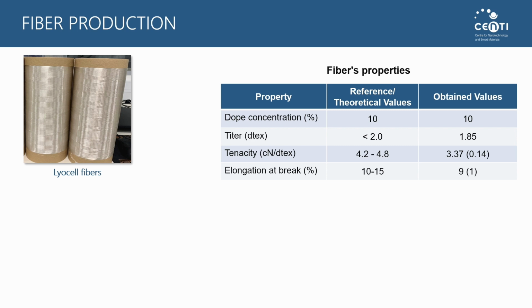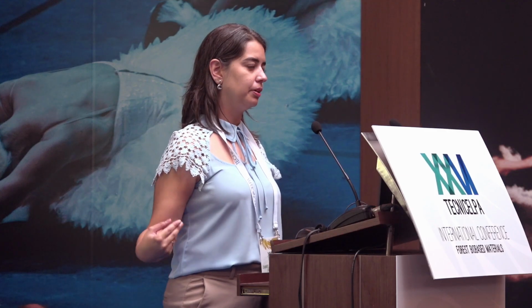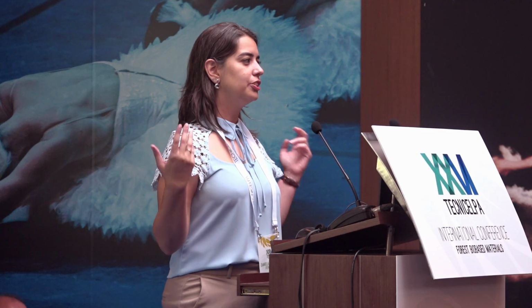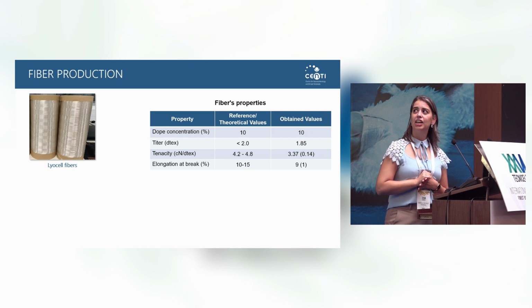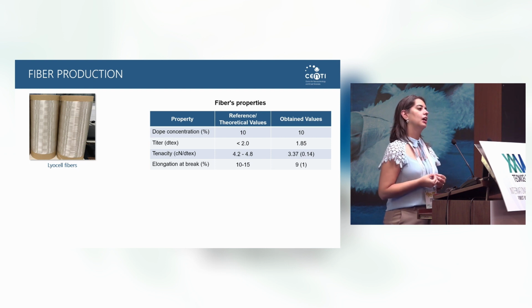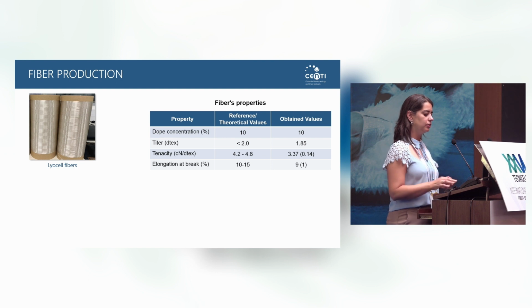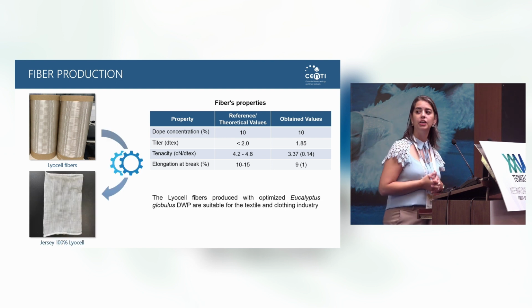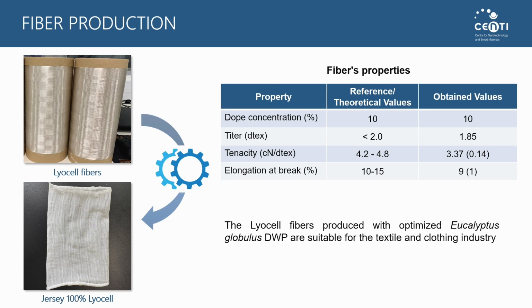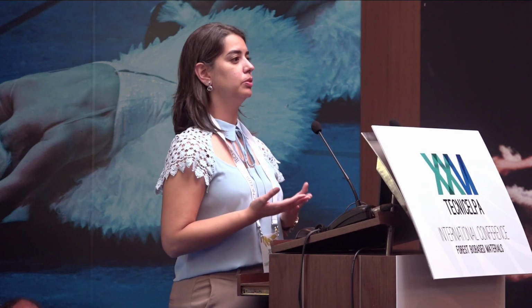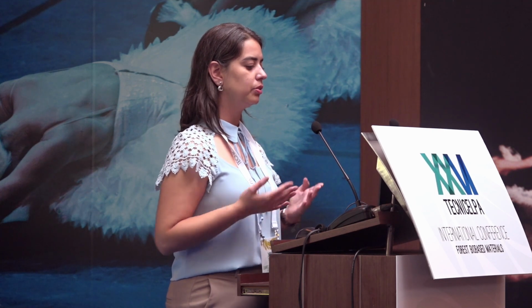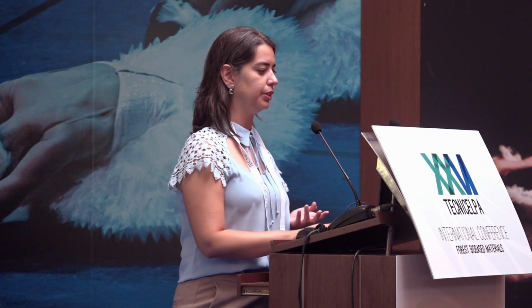So we got our fibers, our first 100% Portuguese fibers made with pulp produced here in Portugal. It was dissolved here and also spun here in Portugal. We used a dope concentration of 10%, and we got fibers with parameters good for textile production, and it could be knitted in a jersey with 100% lyocell fibers, proving that our fibers and the eucalyptus globulus dissolving pulp from CAIMA are suitable for the textile and clothing industry.